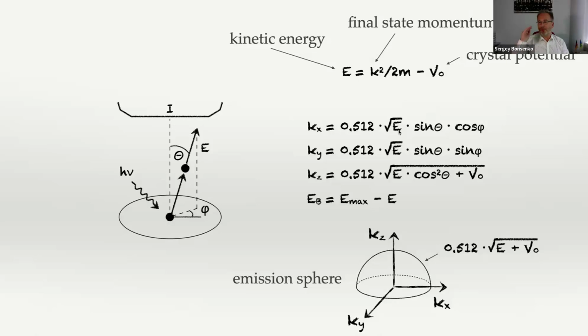When you closely look at these very simple formulas, one could immediately realize that if we fix the kinetic energy of the photoelectron, we just measure only photoelectrons with a single kinetic energy, and they will correspond to a sphere in the reciprocal space. When we are talking about spheres in reciprocal space, one could of course immediately mention the Ewald sphere, and Ewald himself called this the reflection sphere. In certain analogy to this, we will call it the emission sphere. The radius of this emission sphere is also straightforward. You could see it directly from here. It means that only the portion of K space which sits on top of the sphere becomes accessible.